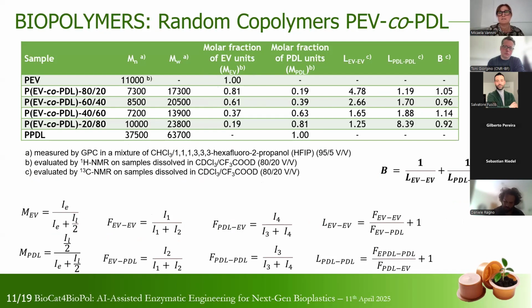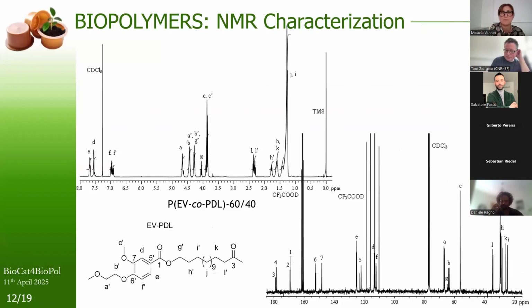It's significant that the calculated molar composition is perfectly aligned with the feed molar amount. Therefore, this indicates the success of our double way of polymerization. Moreover, starting from the monomers, the randomness degree is around 1, so we obtain random copolymers.